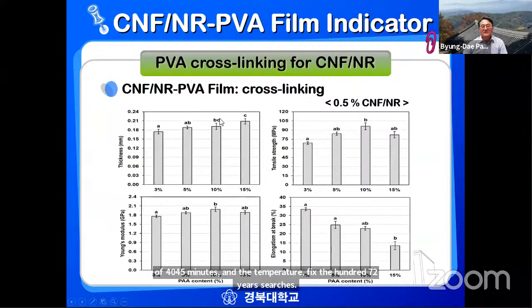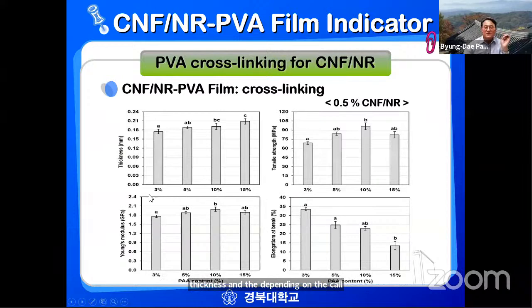And then we have this kind of film and measured the thickness, depending on the cross-link PAA concentration from 3%, 5%, 10%, 15%, and 20% was too much, so we just reduced to 15%. And also we measured the thickness, tensile strength, Young's modulus, and elongation at break. As you see here, when you increase the PAA, obviously the tensile strength increases because of the increased cross-linking density. But above 10%, it decreases. Young's modulus increases a little bit up to 10% PAA, but decreases later. But elongation obviously decreases with increasing PAA concentration because it's used as a cross-linker.